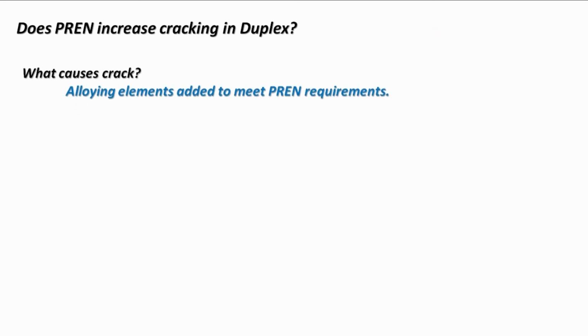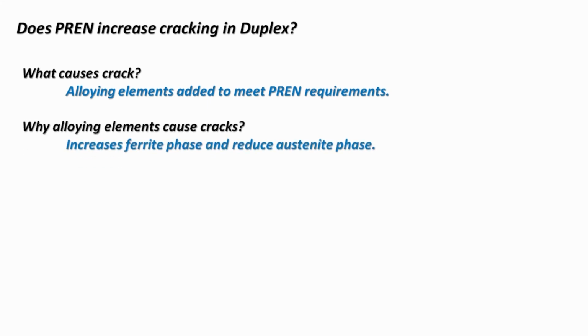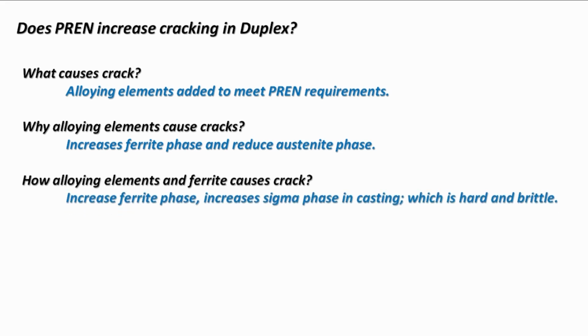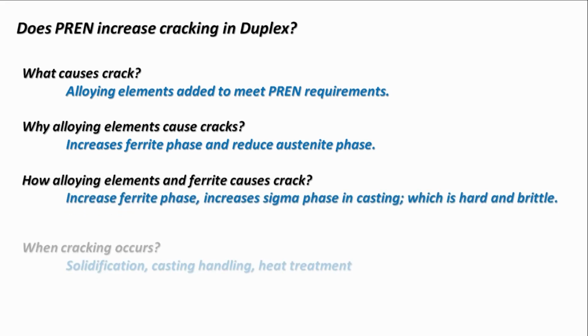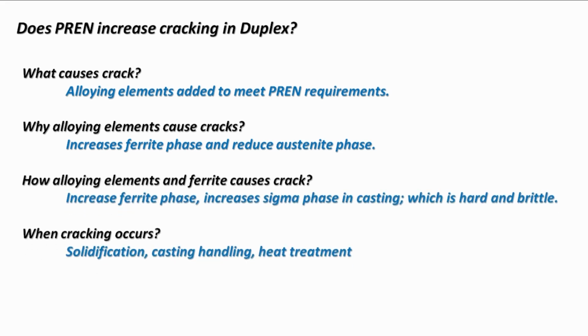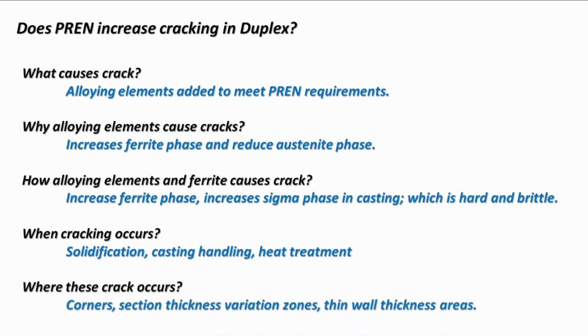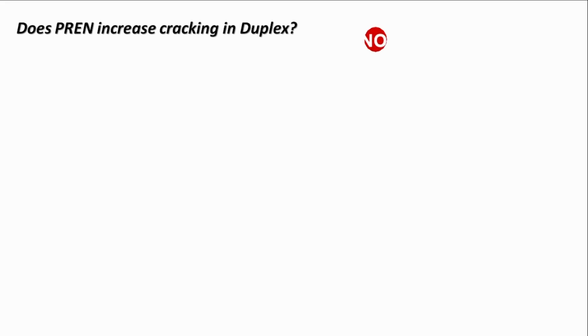So PREN is a problem because of the alloying elements that we add to meet the PREN number. The elements we add are chrome, moly and tungsten, which increase the ferrite phase, which subsequently increases the sigma phase, which is hard and brittle. So when cracking happens, it happens at solidification, casting, handling and heat treatment, and it happens at corners, section thickness variation zones, thin wall section zones, under risers.